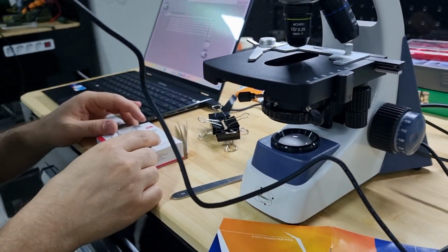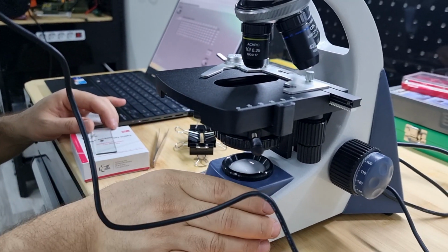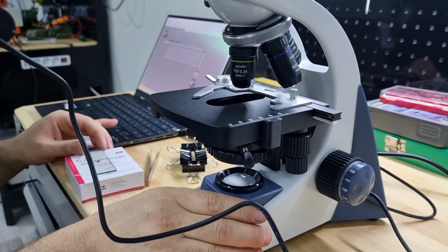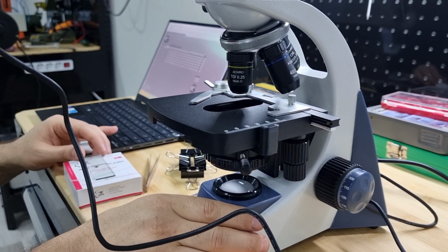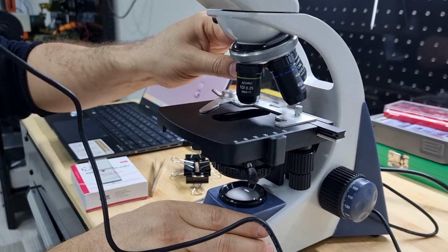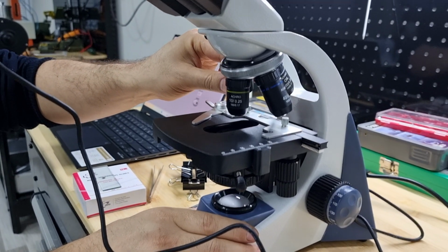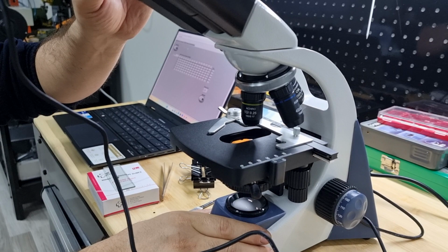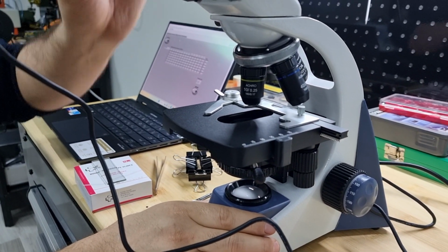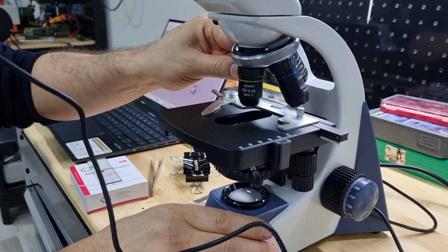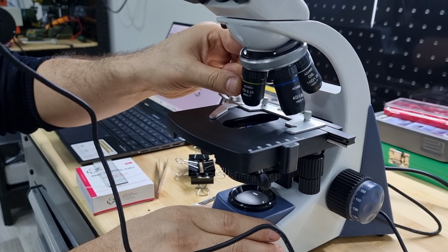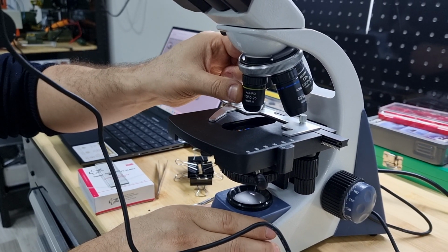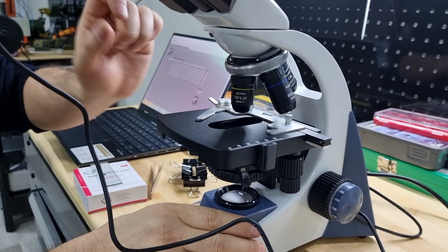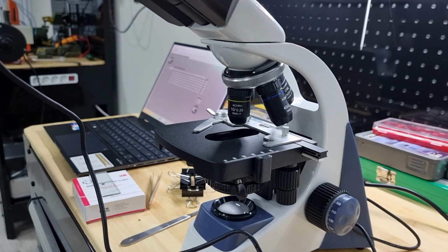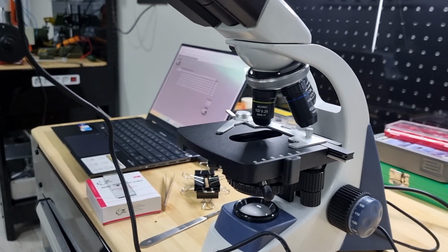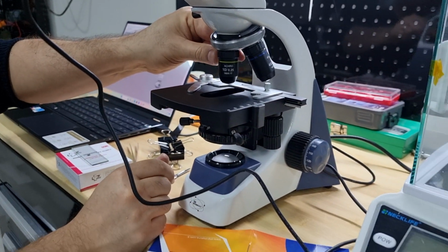Then you will go through microscope. A standard microscope is needed. The magnification according to the norm will be 100. If you have a CCD camera with 10 magnification, you need to set the eyepiece to 10. Then totally you will have 100 of magnification. Total magnification will be 100.